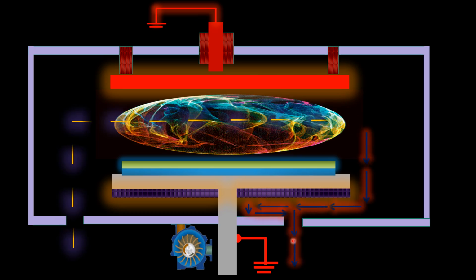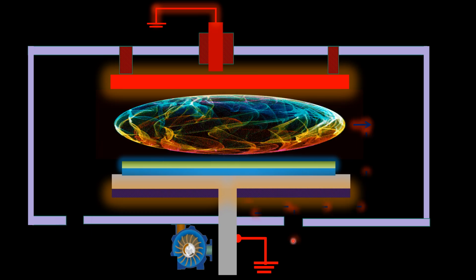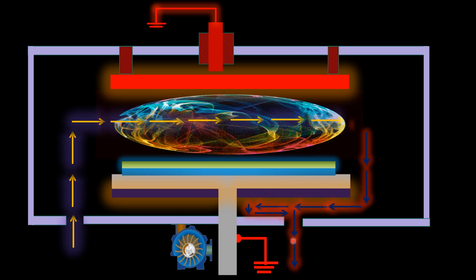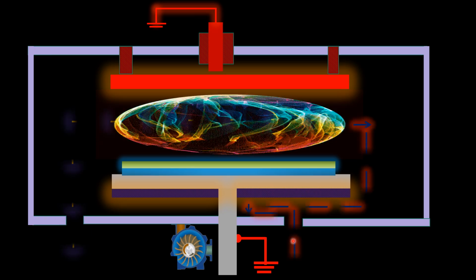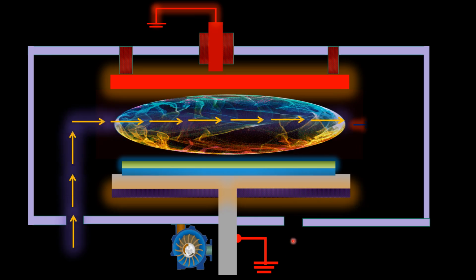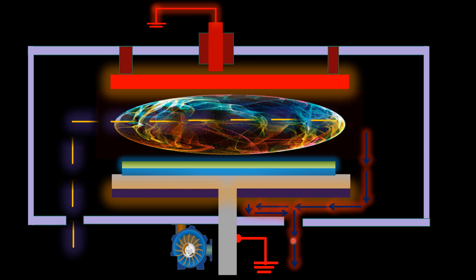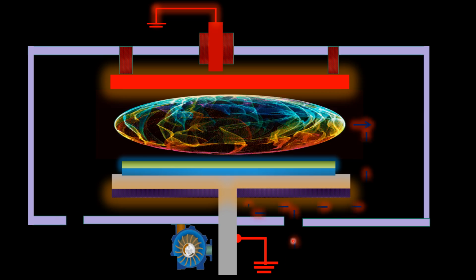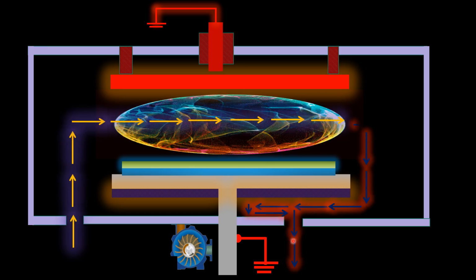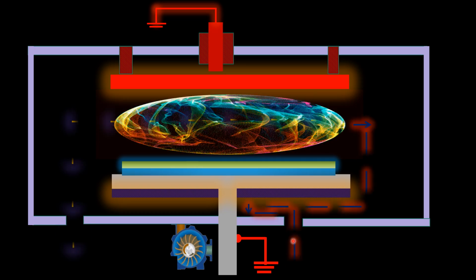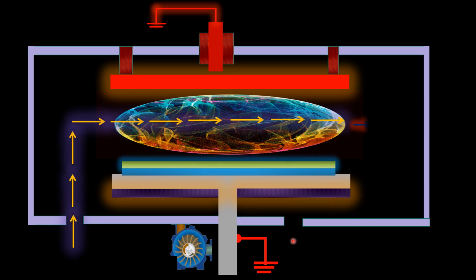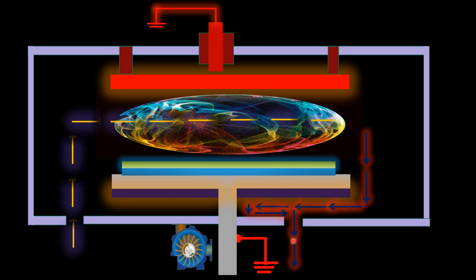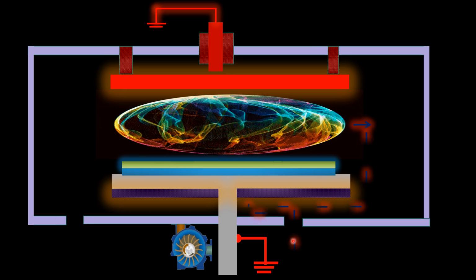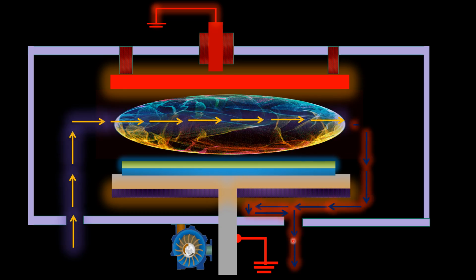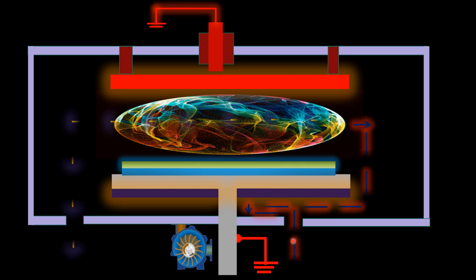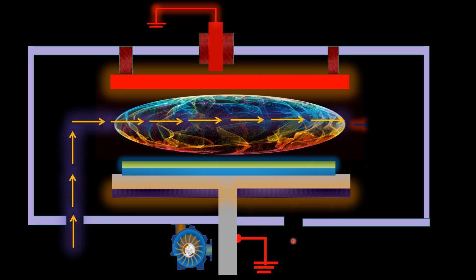So dear student, if you want to prepare a thin film with a PECVD system, initially you need to evacuate the PECVD reaction chamber, and then you need to apply high potential between the top and the bottom electrode, and after that a gas precursor will be incorporated between the top and bottom electrode of the PECVD system. So the precursor gas, due to high potential, will be converted into a plasma, and that plasma becomes chemically active, and it will be deposited on the surface of the substrate. So in this way you will get a thin film on the surface of the substrate. After completion of the deposition, you will de-evacuate the reaction chamber of the PECVD system, and after that you can remove your sample from the PECVD system.